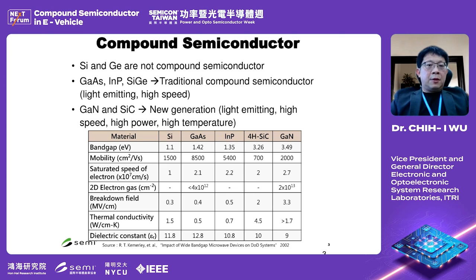If you look at the table at the bottom here, for silicon, the bandgap is 1.1 electron volt. For the traditional compound semiconductors, like gallium arsenide and indium phosphide, the bandgap is also 1 point something electron volt. Although gallium arsenide and indium phosphide can deliver higher mobility, up to close to 10,000 cm squared per volt second, because their bandgap is relatively small, the breakdown field is relatively small.